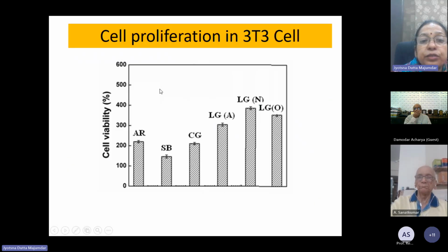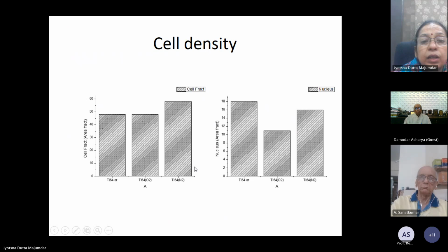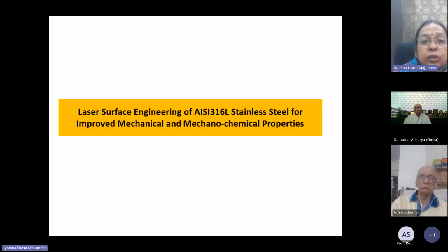When we looked at the proliferation rate, we found that the nitrogen atmosphere offered maximum cell growth rate, even compared to sandblasted and as-received samples. The circular group sample didn't show very promising results. The takeaway of that study was that linear texturing was a very promising technique for improving cell attachment, proliferation and growth behavior, and it also offers very good corrosion resistance and tribocorrosion properties.